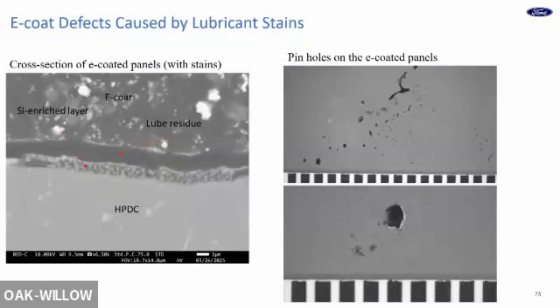So how might the staining affect the performance? Why do we care about this heavy staining? So this is the e-coat sample. This is the cross-section of the e-coat panel, and here is the e-coat. This is the metal substrate, and this is the staining, and this is the porous structure we showed before because of etching. You can see the lubricant staining can stay between the e-coat and the metal substrate or the conversion coating. In theory, the e-coat should bond with the conversion coating, not with the lubricant residue.